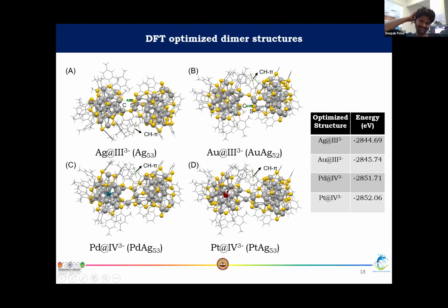Just one question: when you are doing the mass spec, how are you trapping this dimer, by providing some particular energy, or how do you trap that dimer? This is by mass selecting the dimeric species in the quadrupole. Have you observed even bigger masses like trimer, tetramer, anything, even in a small quantity? No, we have not observed any trimer, tetramer.